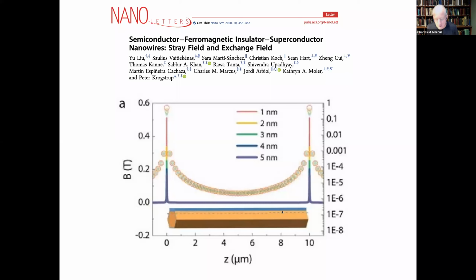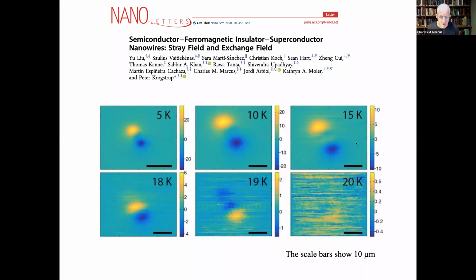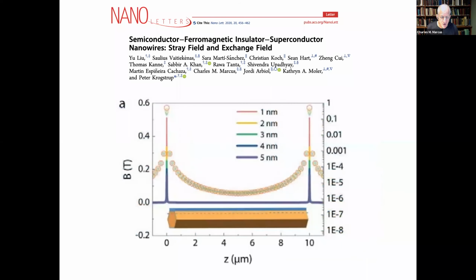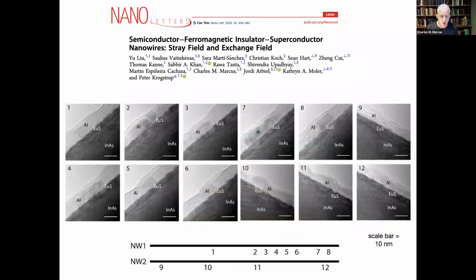So this is what you'd expect from a ferromagnet. The north and south poles of the ferromagnet are where the field emerges, not anywhere along the middle. And that was borne out: it's not a bunch of domains flipped when this was cooled in an external magnetic field, it's uniformly magnetized with the magnetic fields only coming out the ends. So that's what's going on with the magnetism inside of these wires.